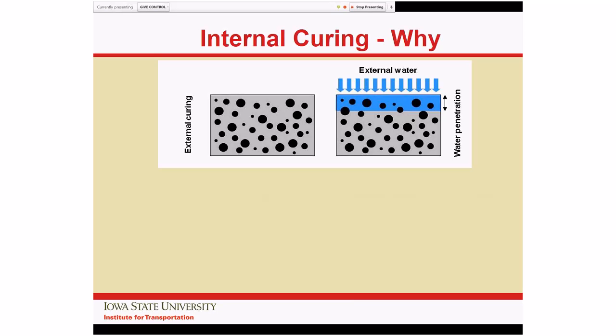Internal curing is an interesting concept. Traditional curing is where we're trying to either seal it up on the top surface or add additional water on the top surface. And in some ways, this may set up a differential because the external water is only coming in at the top. And as you can see in the image, it only reaches in an inch or two. And so you could have a fairly wet environment on the top and possibly a drier environment on the bottom. Again, setting up a differential that's not entirely desirable.